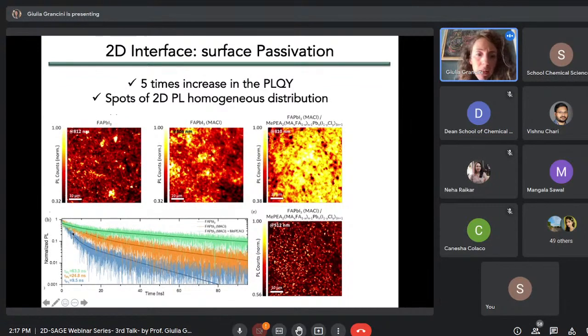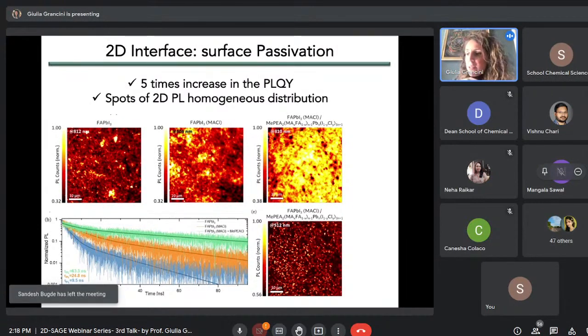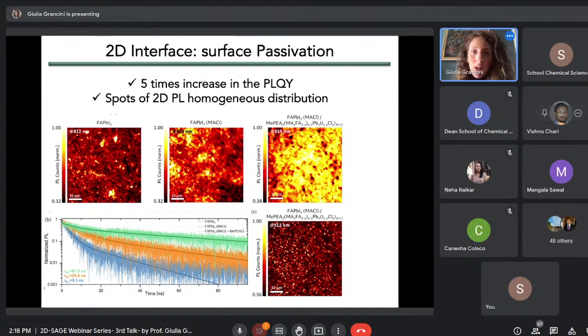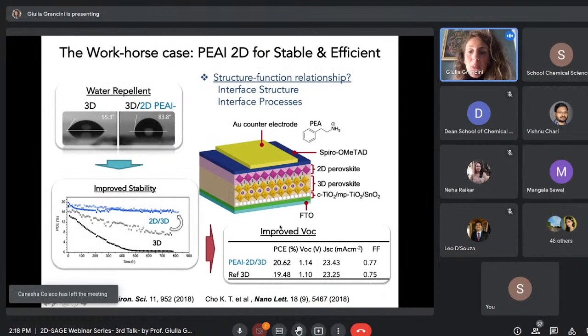So you can see here by the photoluminescence lifetime, which is the key to improve the device VOC and the device performances. So with the addition of this 2D layer, the key message is that the 2D layer does not only improve the hydrophobic character of the surface, but it also improves dramatically, by surface passivation, the surface quality, increasing the photoluminescence quantum yield, thus reducing the losses, which in turn leads to this improved VOC that we always see when we have the addition of this 2D layer on top of the 3D.